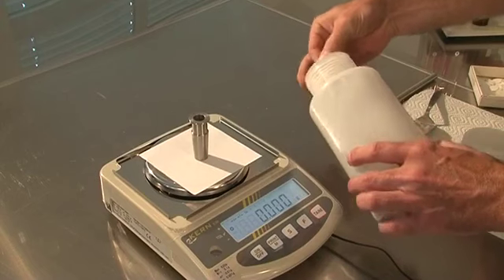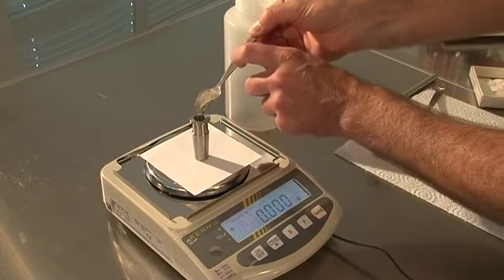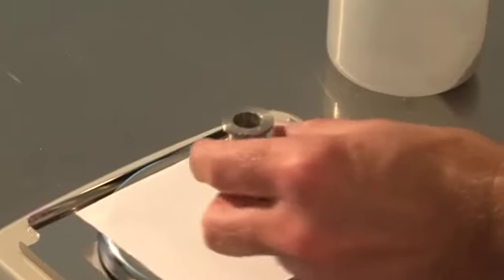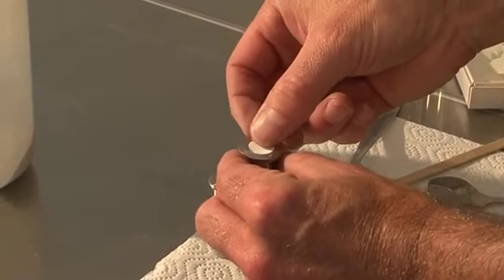The cement mass M1, calculated according to equation 2 for the cement bed to be prepared, is accurately weighed out to 0.001 grams and filled into the cell. The powder bed is levelled by lightly tapping the cell wall. A second filter paper is placed on the levelled surface area.